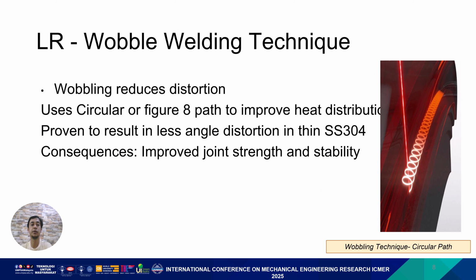Second literature review is about the wobble welding technique. So wobbling is proven to reduce distortion. Wobbling uses a circular or figure-8 path to improve heat distribution, and it proved to result in less angle distortion in thin SS304, and as a consequence, it will improve joint strength and also stability of the weld.